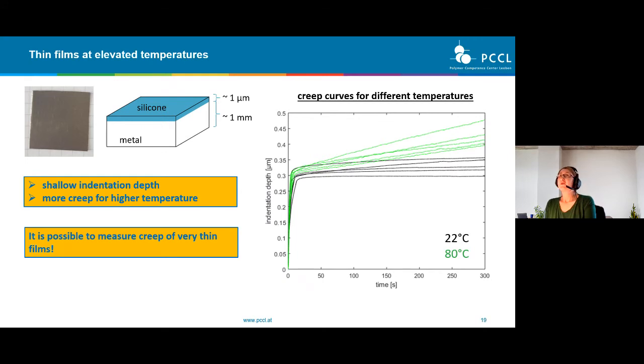As a next topic, I want to show you thin film investigation at elevated temperatures. We had here a metal sample, which was covered with 1 micrometer silicone, and we wanted to get creep curves at different temperatures from this very thin film. And you can see here on the right side, we got creep curves here for 22 degrees and also for 80 degrees. We got these creep curves for really shallow indentation depths, which are only 0.3 micrometer. And we got also for the 80 degrees more creep for higher temperatures. So the outcome of these experiments was that it is possible to measure creep of a very thin film.